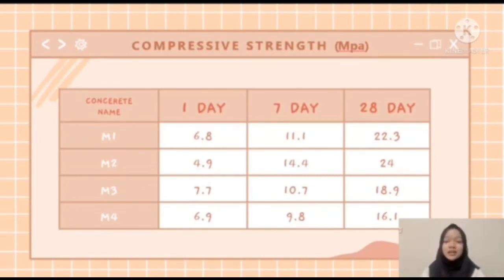From the compressive strength test, it can be concluded that compressive strength was higher than control concrete for 5% eggshell powder replacement at 7 days and 28 days of curing ages. Eggshell powder replacements greater than 10% had lower strength than control concrete. So this is what we can conclude from the table of compressive strength.